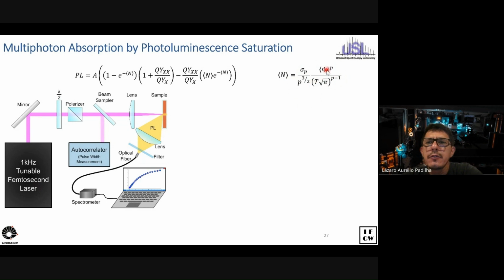So basically you have 3 parameters, and all 3 parameters come from your laser. So at the end of the day, you don't need any parameter from the sample itself. So your only relative error between 2 different samples, if they are measured at the same time, comes from the fitting parameters, not from the actual measured